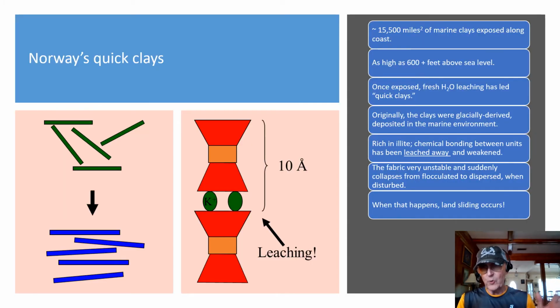Now here's the problem for Norway. There are more than 15,000 square miles of marine clays that are now exposed along the coastline of Norway. And some of these clays are now located as high as 600 feet above sea level. Once exposed above sea level, freshwater has leached these marine clays, turning them into the quick clays. Originally, the clays were glacially derived, deposited in a marine environment.